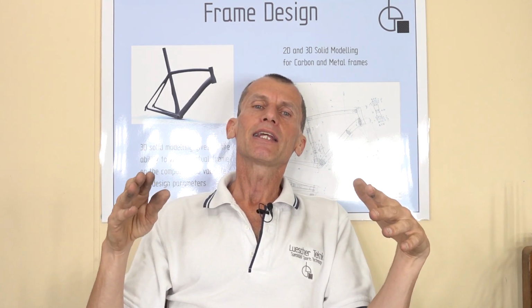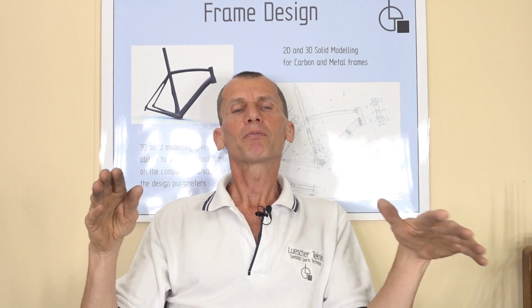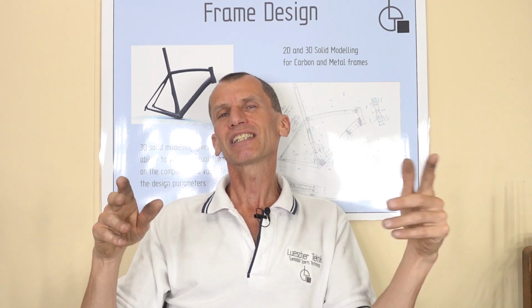So, other things that affect the rate of bleed, like are you allowing enough flow of the resin, and a whole bunch of other variables. But anyway, if you vary that resin content by much from the optimum resin content for the specific fabric type being used, it leads to some reduction in structural properties and other concerns. So for more information on that, have a look at the videos I did on resin rich and resin dry for some further info. As it sort of explains having too much and too little resin.